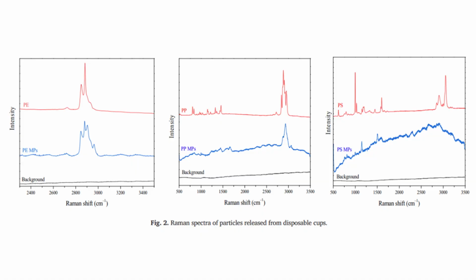Spectroscopy showed that the particles released from the polyethylene-coated cups were consistent with polyethylene, indicating that polyethylene was likely being released from the lining of the cups. Similarly, the spectra of the particles released from the polypropylene and polystyrene cups were consistent with polypropylene and polystyrene. And therefore, the author stated that these results affirm that the particles originate from the plastic material of the cups, and the leaching of the microplastic particles into the contained beverage from the disposable cups is clearly verified.